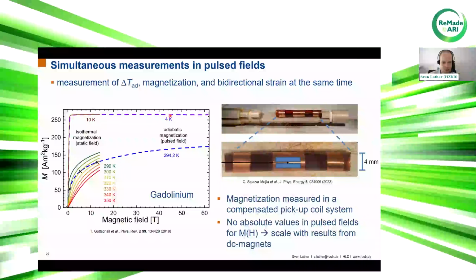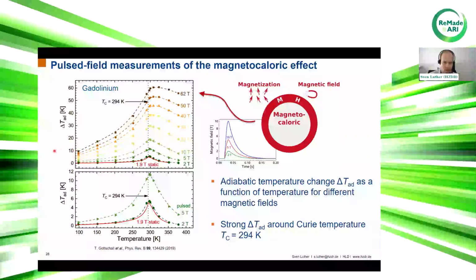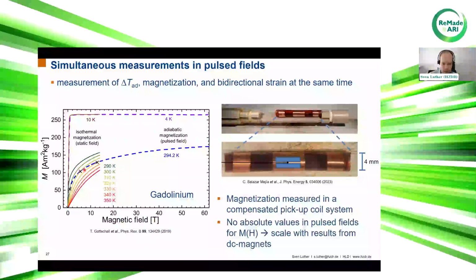As you can see here, at low temperatures, for example at 4 Kelvin, there's no difference between the static and the pulse fields, because at low temperatures there's no dramatic temperature change or adiabatic temperature change. But if we go to higher temperatures, this is a pulse field measurement at 294 Kelvin, so around the Curie point. You can see we have a deviation of the pulse field magnetization over field from our static field measurements,